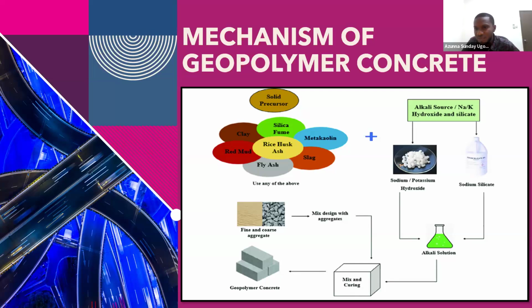Then after that, the next major thing in geopolymer concrete is the alkaline activator solution. You can simply call it the alkaline solution. Now, how is this alkaline solution produced? It's a combination of sodium hydroxide or potassium hydroxide and sodium silicate. So if you want to produce geopolymer concrete, after you've done your mix design, you get the weight of your precursor or your binder per se, combined with your alkaline activator solution, which is sodium silicate and sodium hydroxide.